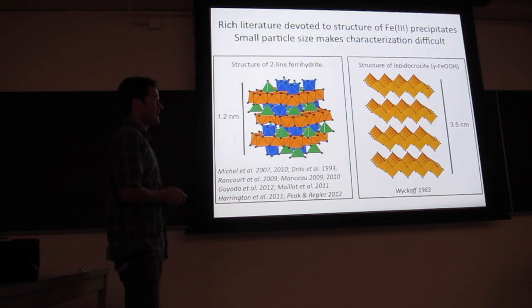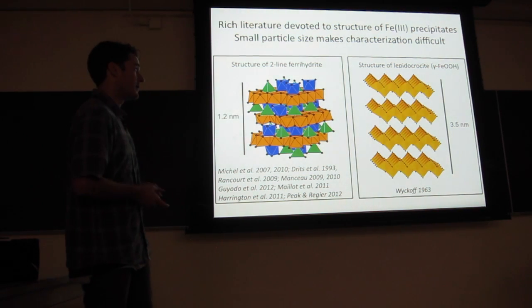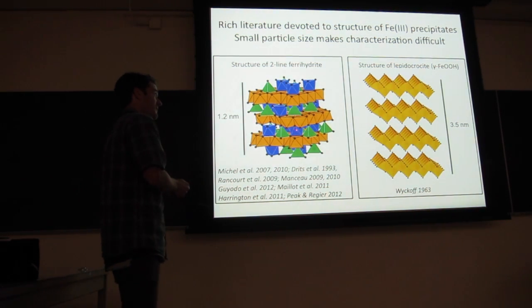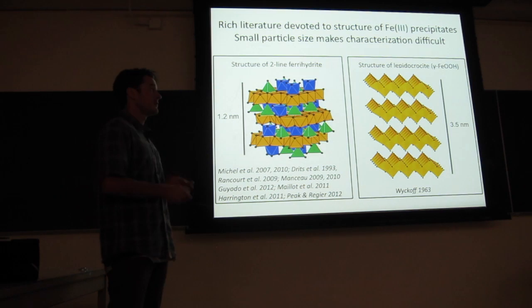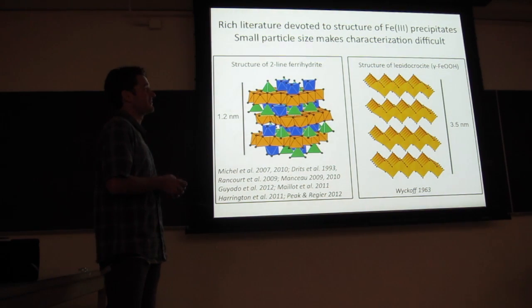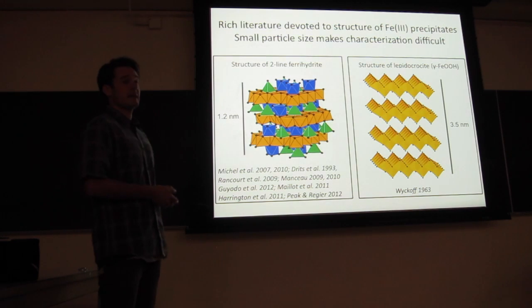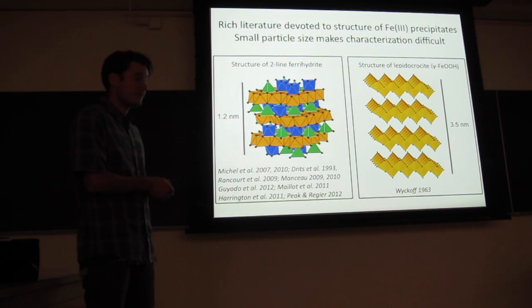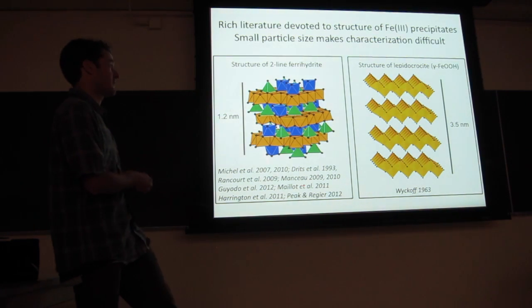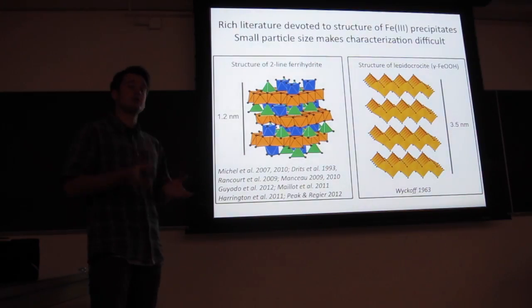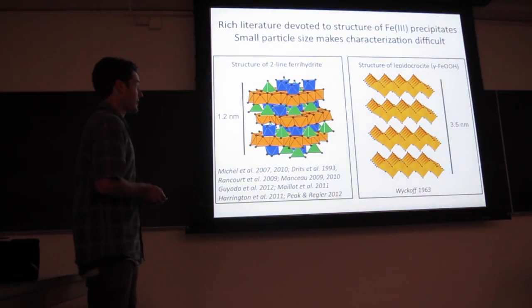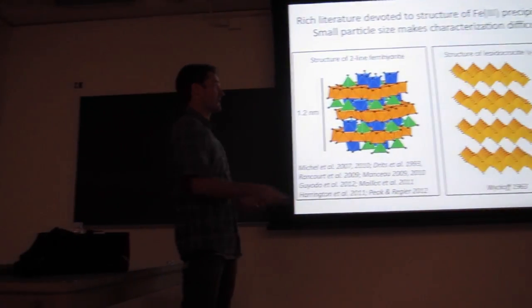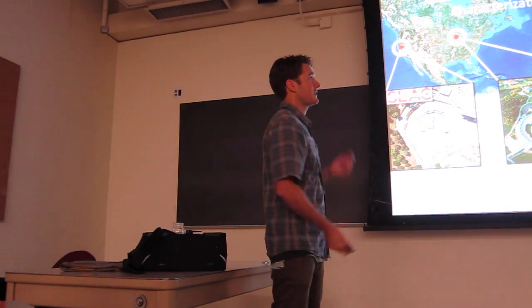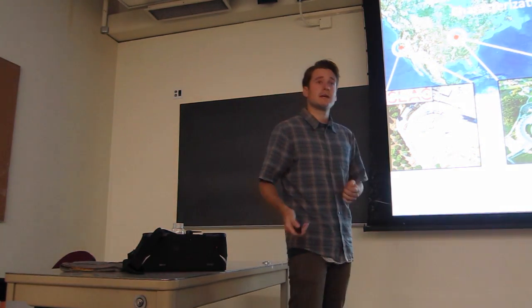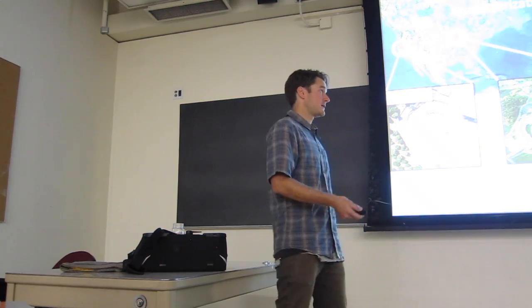Lepidocrocite is an iron oxyhydroxide that, when you compare it to 2-line ferrihydrite, is pretty well behaved. All of the atoms are where they're supposed to be. It's a very ordered and crystalline material, and we've known the structure of that for decades. This is because we can use X-ray diffraction to look at this, but we can't use X-ray diffraction to look at this one because it's too disordered and too small. So that forces us to use non-traditional techniques. And in my case, I use synchrotron-based X-ray characterization techniques.